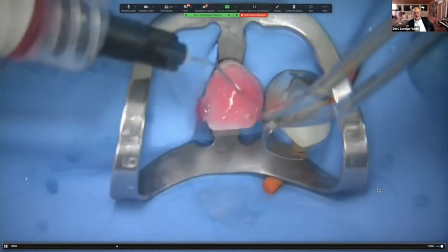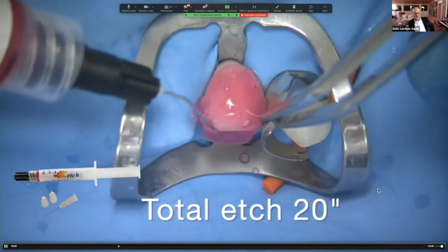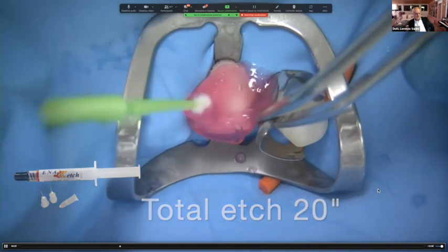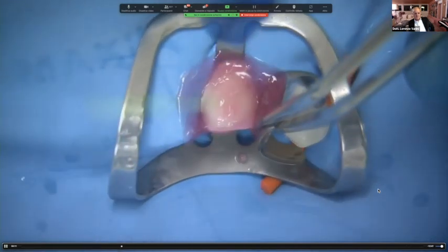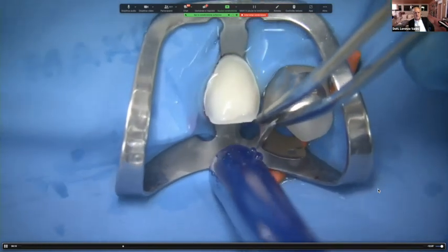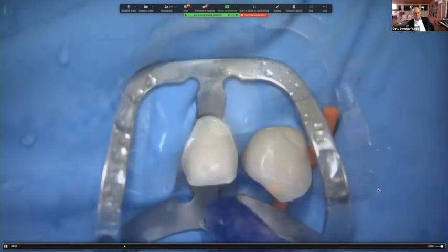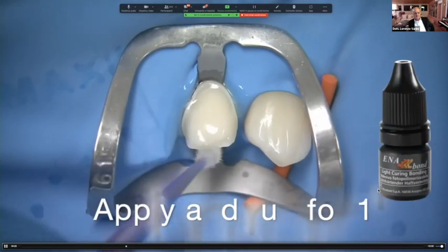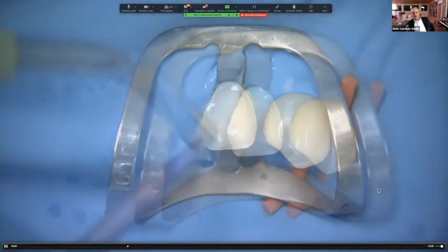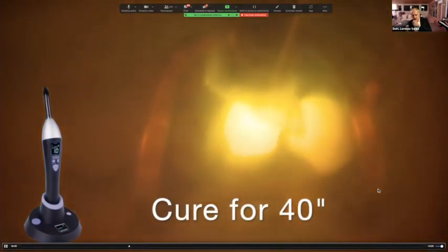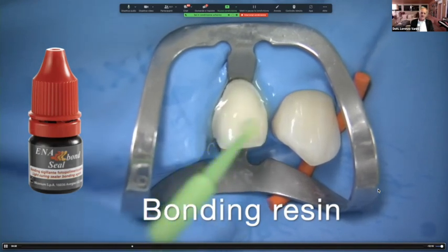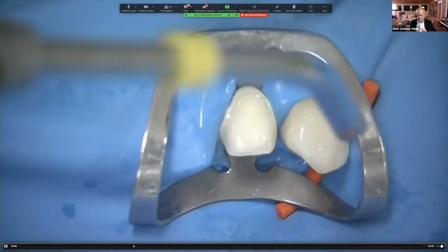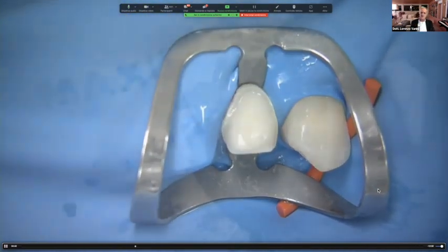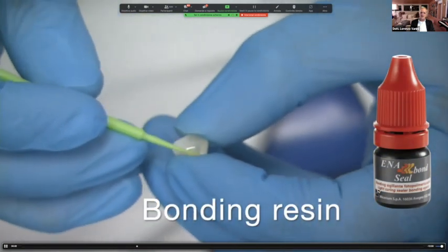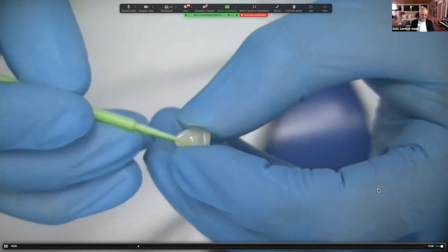The tooth adhesive phase starts with the etching of the surfaces. 20 seconds. Rinse very well with water. You have to apply and rub for 1 minute and then cure for 40 seconds minimum. So you have sealed very well. Now a layer of bonding resin. Blow air in order to have a thin layer, but you don't have to cure. And a seal also in the laminate.